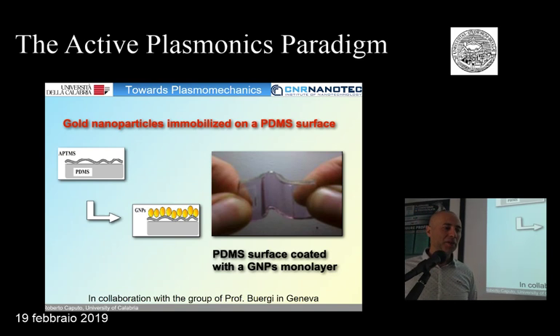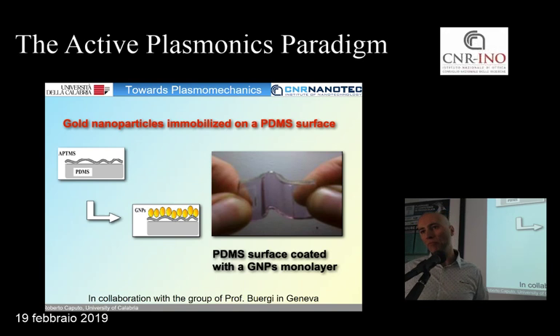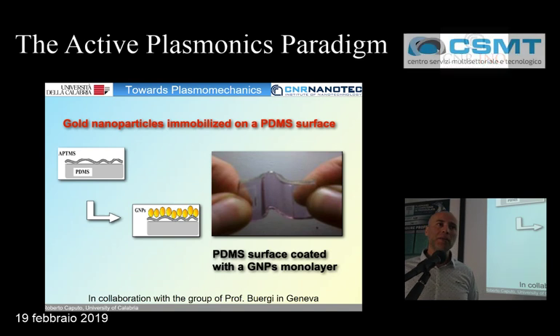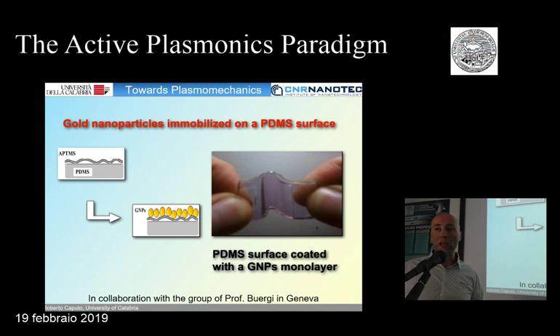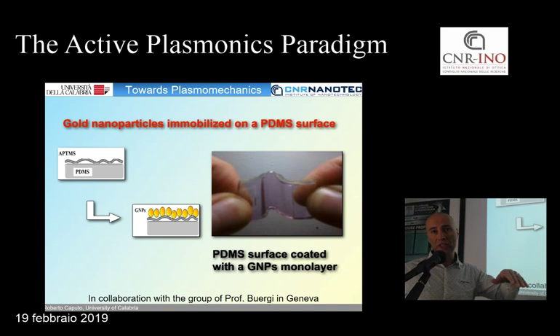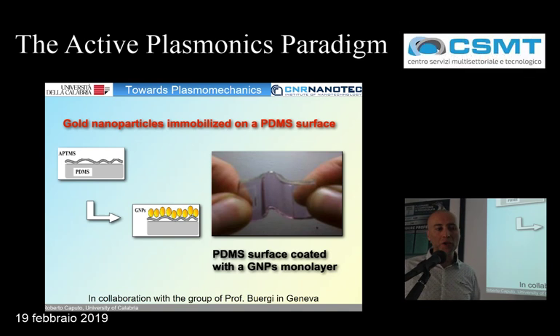And in the last 5 years, we have been collaborating in this direction, because it is very promising for many kinds of applications. In particular, with liquid crystals, the surface is layered with the liquid crystals, so it's difficult to combine the material with other systems, like biological ones, for example. On the contrary, here you have the nanoparticles on the surface of the substrate, and you can put whatever you like, eventually to use the resonance or the resonance shift in a fruitful way.